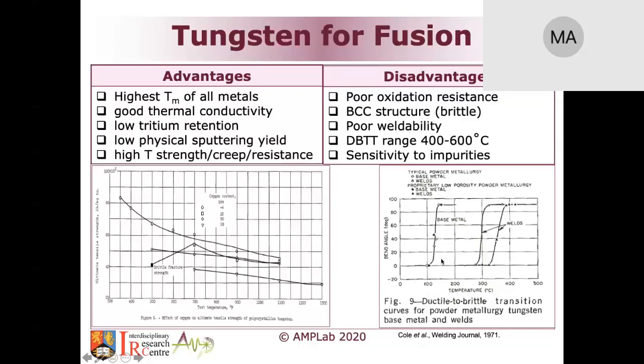But then after welding, where you pick up porosity, oxygen, and all sorts of inclusions, the ductile-to-brittle transition temperature moves to a much higher temperature, meaning that the material becomes brittle at even higher temperatures, not just cold temperatures, as you know in BCC materials.